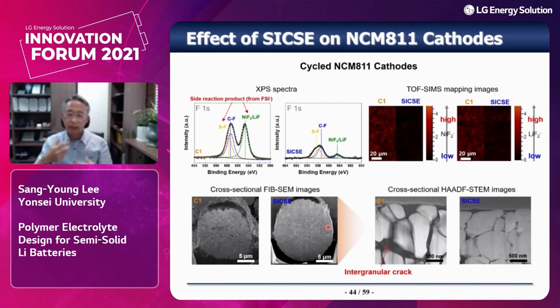So that means the single ion conductor can stabilize the interface with the cycled NCM811 particles. So we can suggest the electrolyte with a high cation transference number enhances the electrochemical reliability of the NCM811 cathode. This is another noteworthy advantage of using single ion conducting polymer electrolyte.